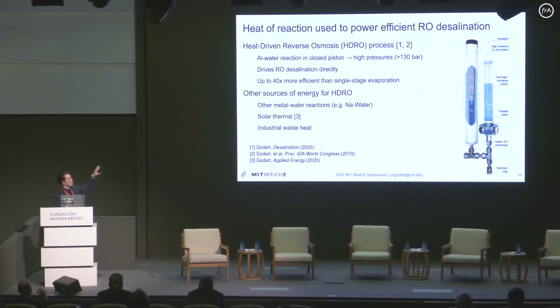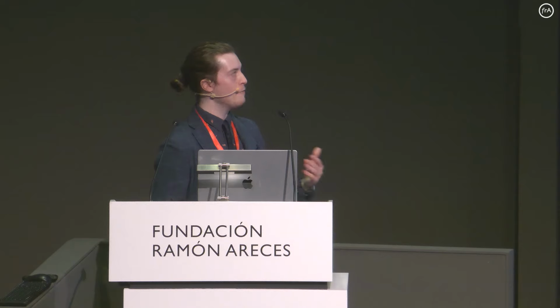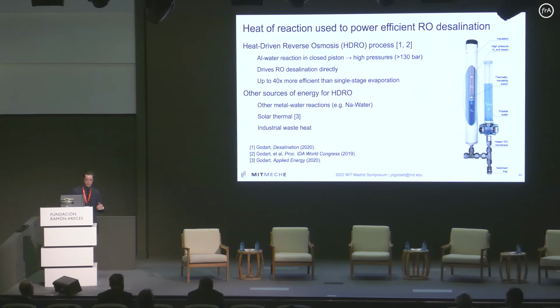And what I came up with is a system that effectively is a giant piston, where on one side of the piston, we're doing this aluminum water reaction. That generates high pressures, which is able to pressurize seawater against a semi-permeable membrane and do reverse osmosis desalination. And it turns out, it's basically a big heat pump, big heat engine, and it's able to do desalination about 40 times more efficiently than just single-stage evaporation, just boiling off the water.